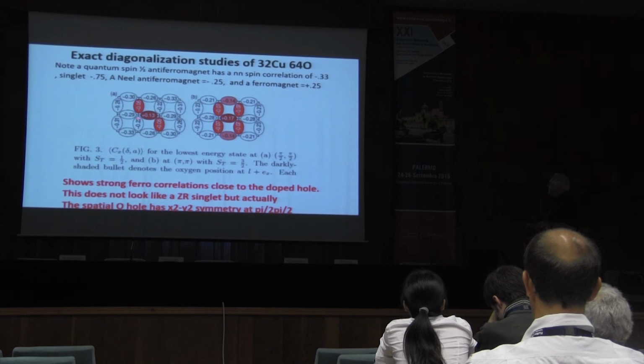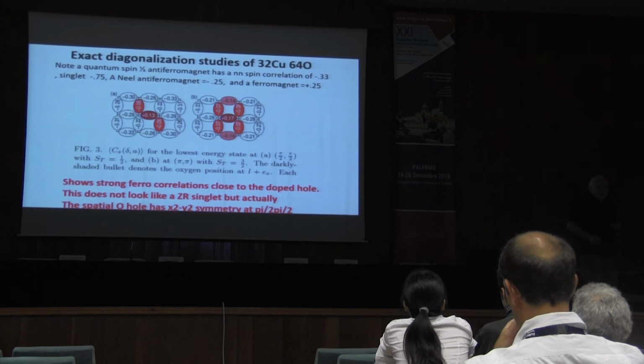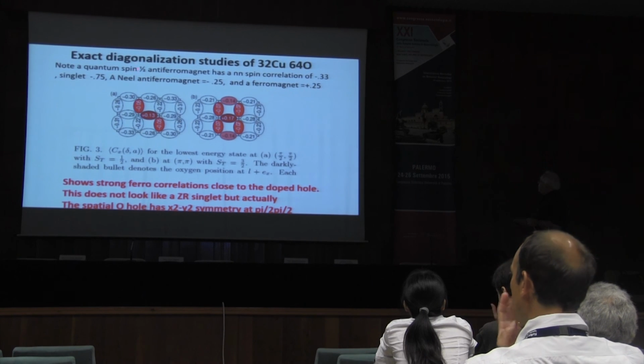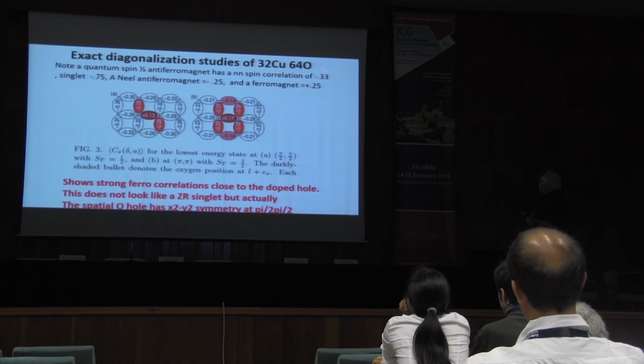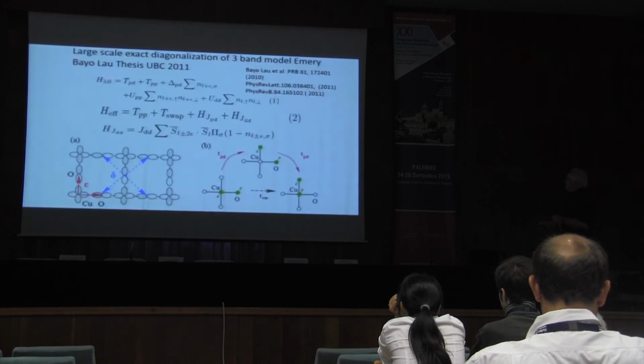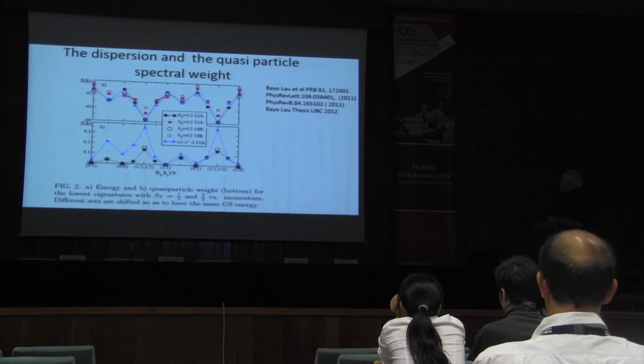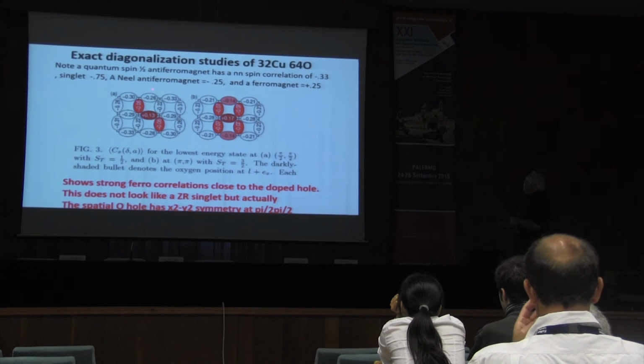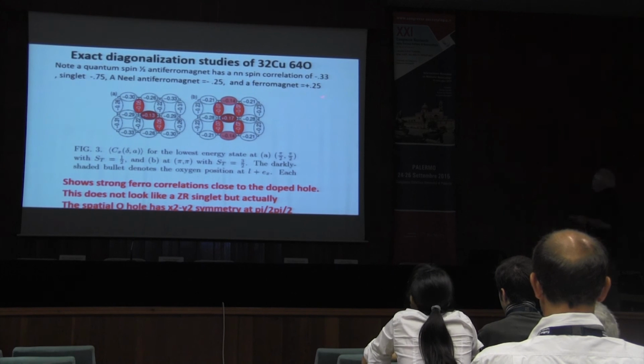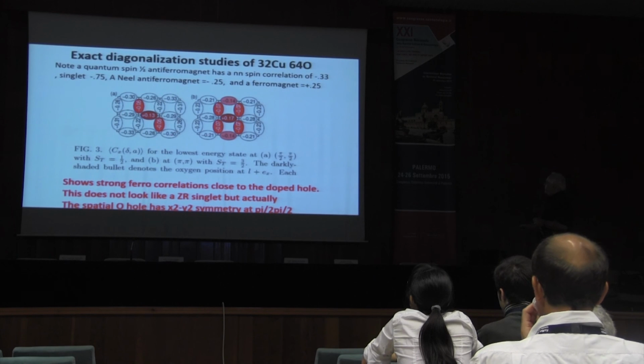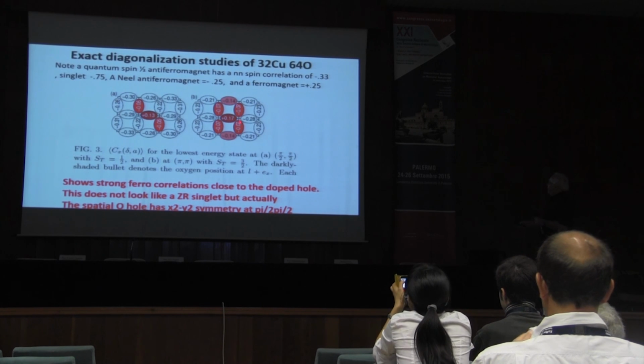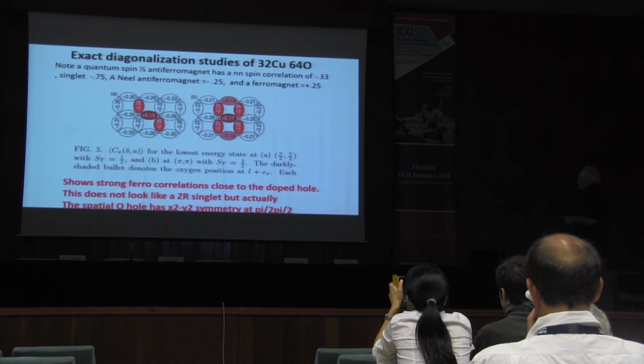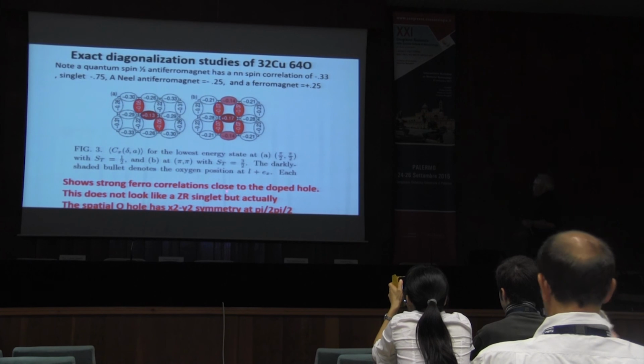Then you find out that these copper spins are very strongly ferromagnetically coupled around that oxygen, right? Whereas they were antiferromagnetic. For a spin-1/2 antiferromagnet with full quantum fluctuations, you get a spin-spin correlation function of minus 0.33. For a singlet, you would have minus 0.75, and for an Neel antiferromagnet, you'd have minus 0.25, and for a ferromagnet, you'd have plus 0.25. This is plus 0.13, or at a different point in momentum space. Remember, these are periodic, okay? But you can still calculate the correlation function, and that is plus 0.17. So these are huge ferromagnetic-like correlations. This shows strong ferrocorrelations close to the doped hole.